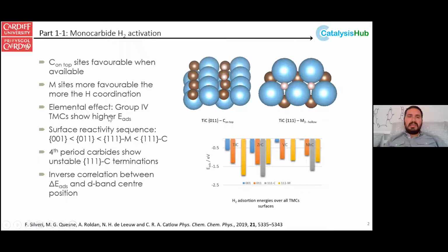As I say here, we found that the dominant surface absorbs hydrogen the least strongly, which, if you think about a hydrogenation reaction, is actually what you want. You want it to hold on to the hydrogen, but you want the hydrogen to be there for further hydrogenation reactions, whereas the 111 surface binds hydrogen very, very strongly. So it may well be that those hydrogens are not available for further CO2 reduction.